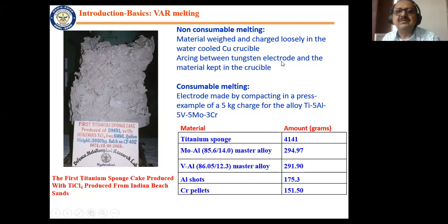Now, as far as melting goes, one of the most industrial processes of melting is vacuum arc remelting. Although there are other methods like electron beam and plasma melting, the most prevalent one, and that is also followed in India, is VAR, vacuum arc remelting. Now, you can melt in non-consumable mode or consumable mode. By non-consumable mode, I mean the electrode does not melt, but there is a tungsten electrode which is attached, and the material is kept in a crucible, and arcing is done after applying vacuum, and it melts and solidifies in the water-cooled copper crucible. And so this type of melting is called non-consumable, and that is only for lab purposes.